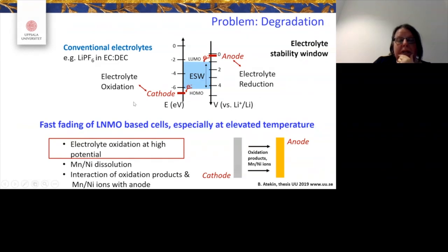Well, one thing one has to look at when it comes to studying this high voltage cathode are the electrolytes. And it turns out that both these two compounds, the ordered and disordered, are rather fast fading, and the electrolyte oxidation at high potential is one cause for this. But despite this, the disordered one is much better. You have also some kind of manganese and nickel dissolution, which means that you actually find the nickel and manganese in the electrolyte and on the surface of the counter electrode. And so you have actually poisoning of the anode. And you see a lot more manganese and nickel dissolution for the ordered one.